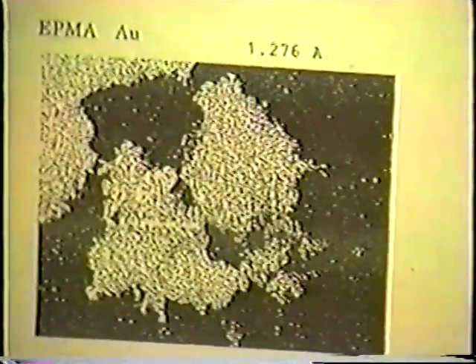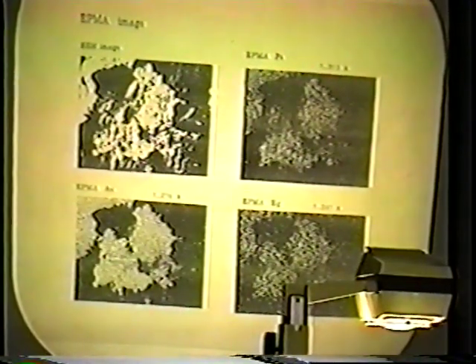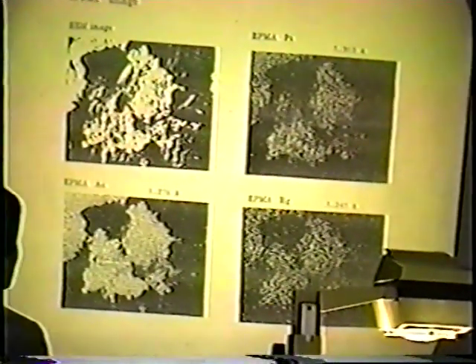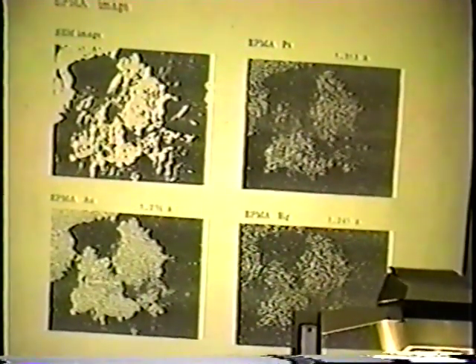This is the EPMA image. In this figure, this is the image of the deposit, and these three figures are EPMA images of gold, platinum, and mercury. As seen from this figure, the EPMA image of gold is the brightest. So we consider that the main component of the deposit is gold, and therefore these deposits are produced at the gold electrode, we consider. And as also seen in this figure, platinum and mercury are contained in the deposit in nearly the same amount.